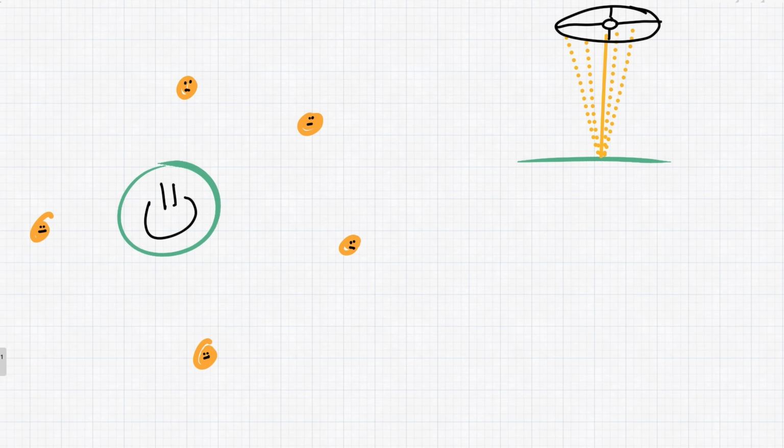Another scenario that can happen is that the electron beam will strike one of the electrons in orbit around this nucleus. The electron beam has a very high velocity because we accelerated it, meaning it has enough energy to kick this electron out of its orbit, and it goes off and gets ejected from the sample. And because the electrons in the beam are negatively charged and the electron itself is negatively charged, there's a force between these two, they're pushing on each other, an exchange of energy. And so the electron, when it leaves its orbit, has been slowed down considerably compared to the initial high energy electrons we send in.